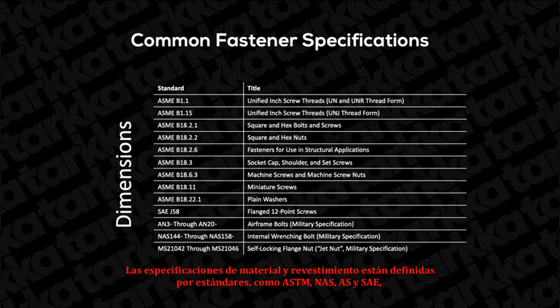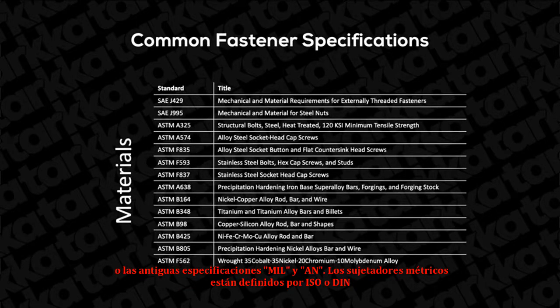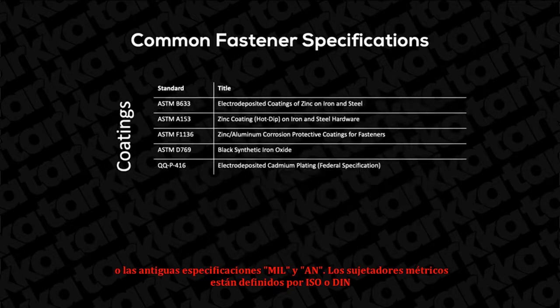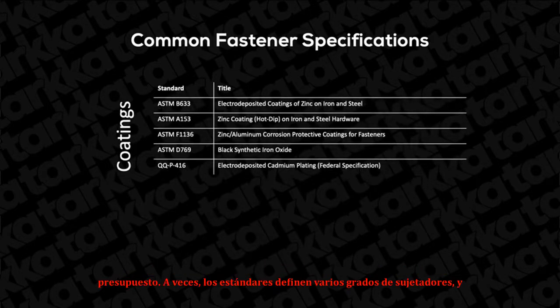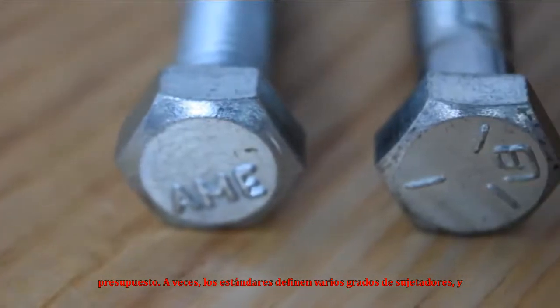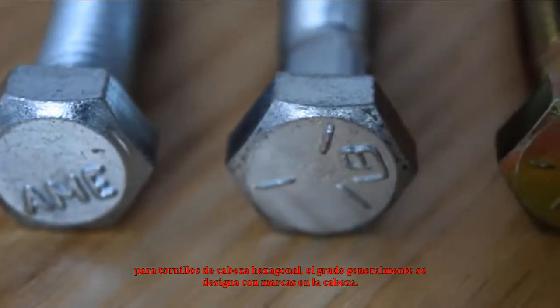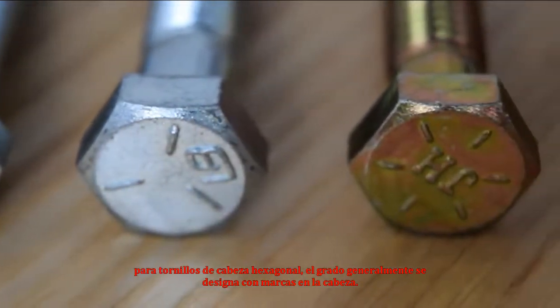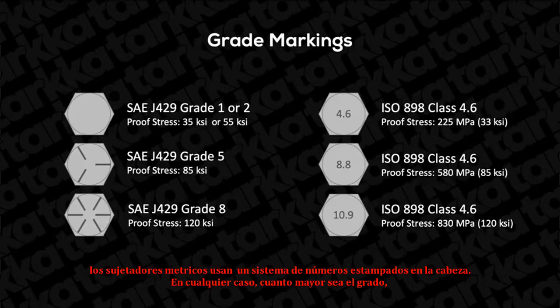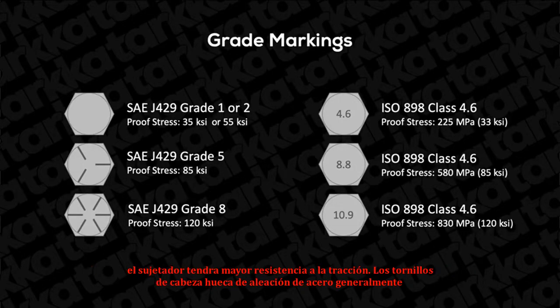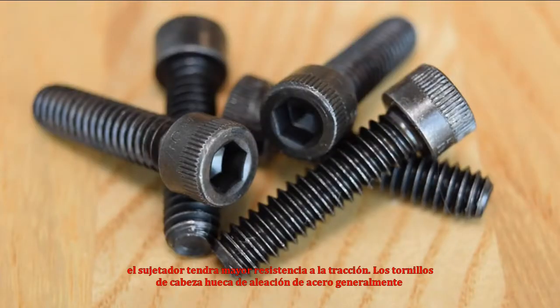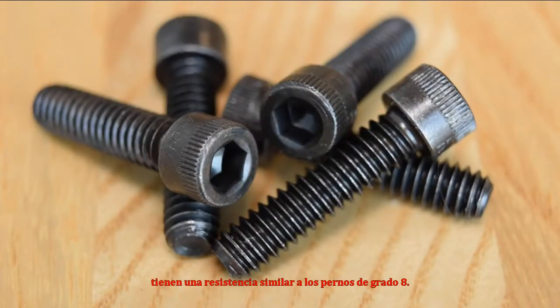Material and coating specifications are defined by standards, such as ASTM, NAS, AS, and SAE, or the former MIL and AN specs. Metric fasteners are defined by ISO or DIN specifications. Various grades of fasteners are sometimes defined by the standards, and for hex head screws, the grade is usually designated by marks on the heads. Metric fasteners use a system of numbers stamped into the head. In either case, the higher the grade, the higher the tensile strength of the fastener. Alloy steel socket-head cap screws generally have a strength similar to grade 8 bolts.